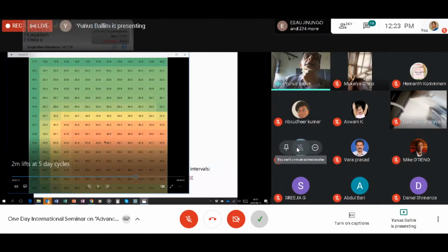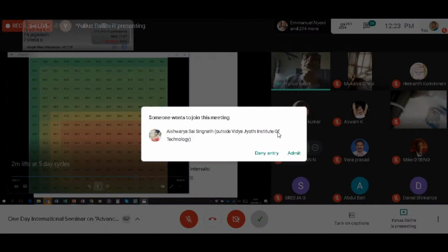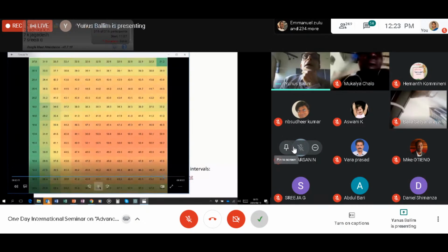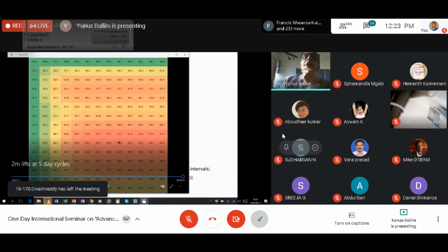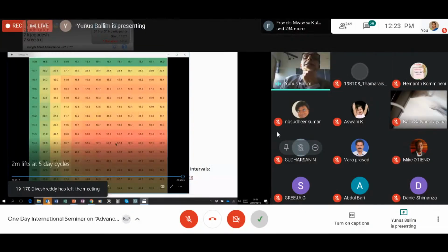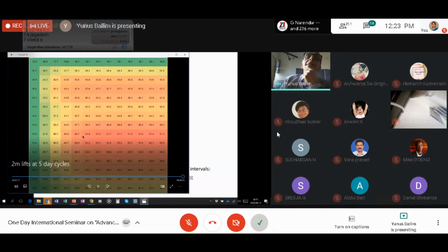And the top layer, the third layer cast, is now already at 25 degrees. And this layer is getting to 48, 49 degrees. By this time, which is about 5 days later, we're reaching about 52 degrees, having started at 20. The big heat is now in the second layer, and that is because it's drawing heat from the bottom and from the top.